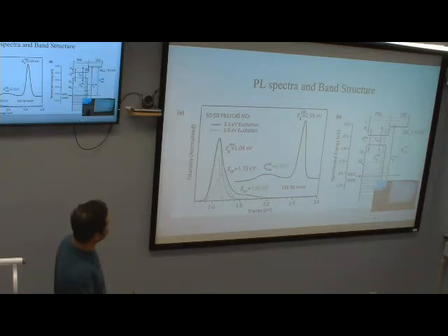This green line is after excitation at two electron volts. This two electron volts is lower than the cadmium sulfide band gap and higher than lead sulfide. So you can assume that it's exciting only these regions. So we are getting the excitation specifically from the lead sulfide portion. This portion overlaps with the overall one. And there's another one, a very long tail one.